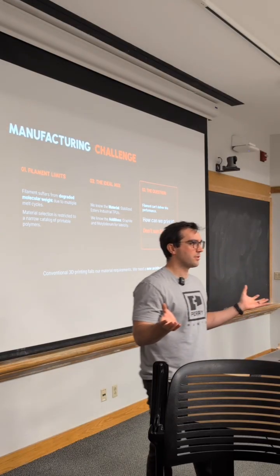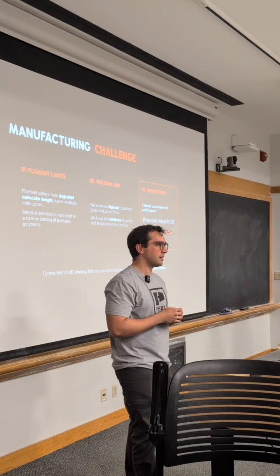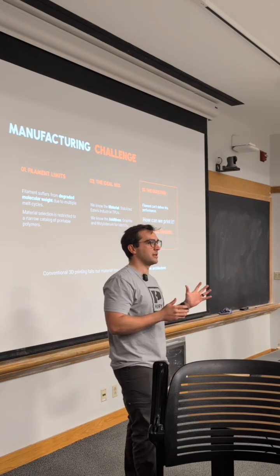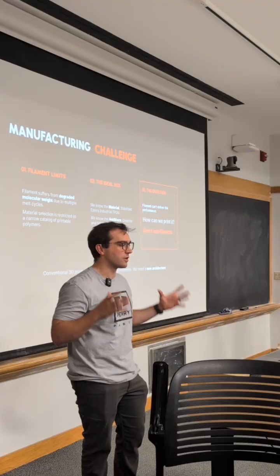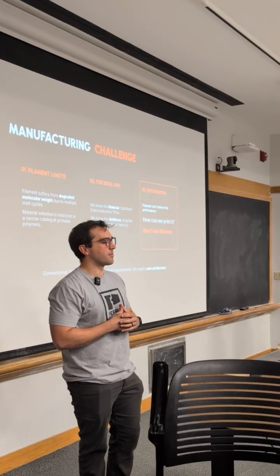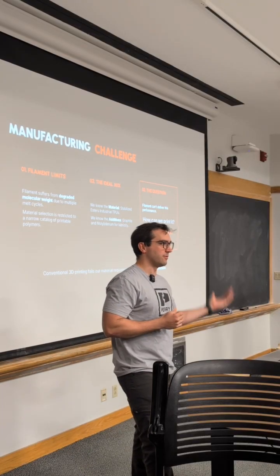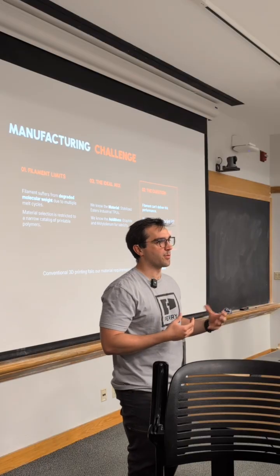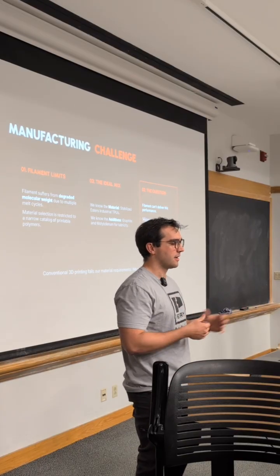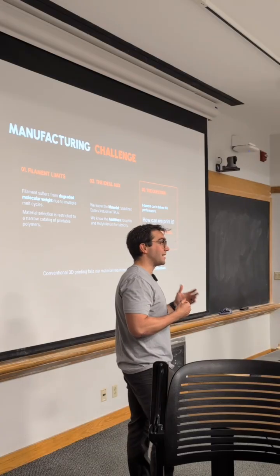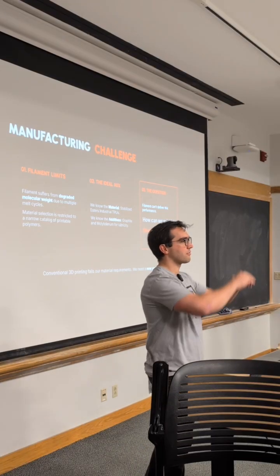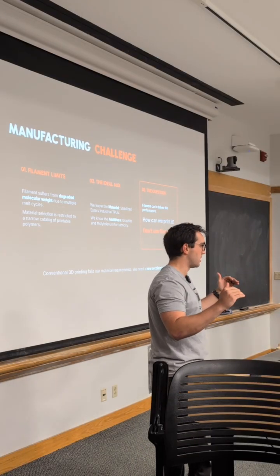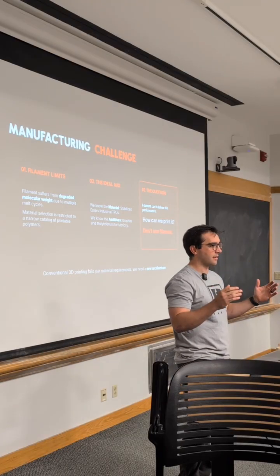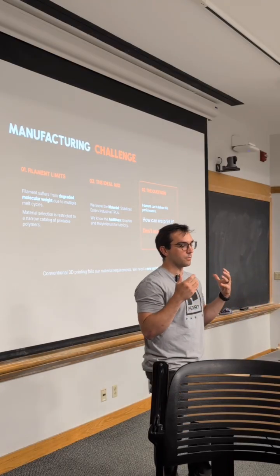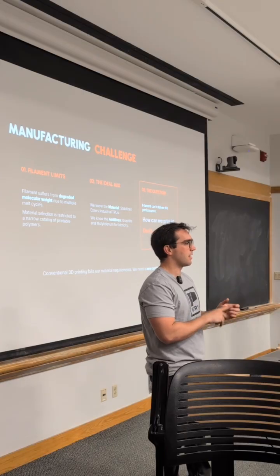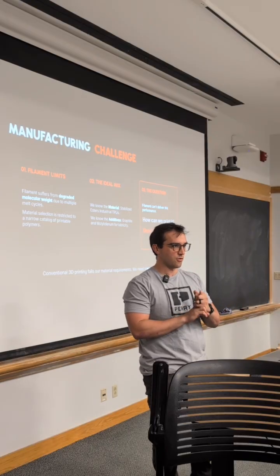So just to kind of pull the material story together, going all the way back to filament and its core deficiency. Filament suffers from degraded molecular weight, right? We've melted the material multiple times, we've broken down those polymer chains, they're less effective. On top of that, we also know that we need a slightly different material, right? We're under the right umbrella, we're under the TPU umbrella, that thermoplastic elastomer, but we need different additives, and we need a different base chemistry.